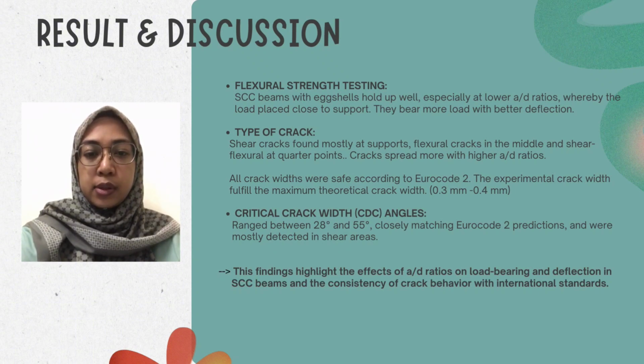All crack widths were safe according to Eurocode 2. The experimental crack width fulfilled the maximal theoretical crack width, which is between 0.3 and 0.4 mm. As for the critical crack angles, they range between 28 degrees and 55 degrees. It is closely matching the Eurocode 2 predictions and was mostly detected in shear areas.